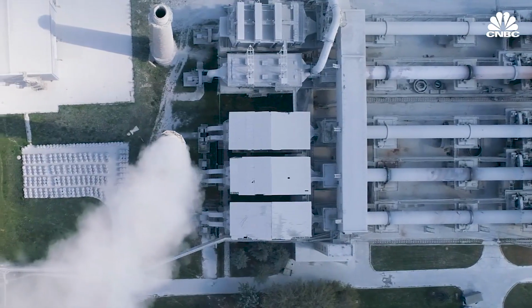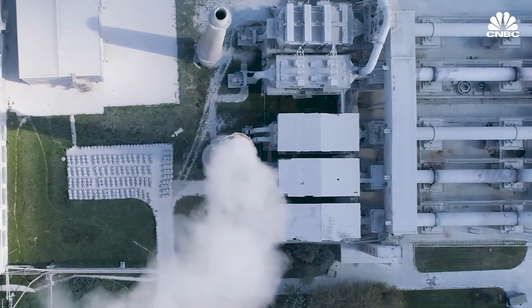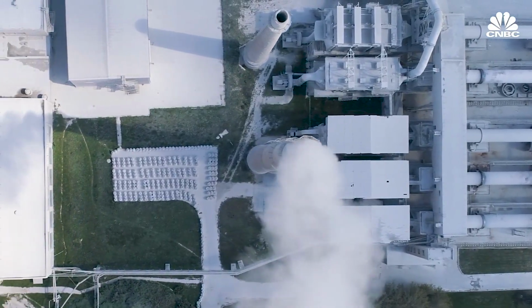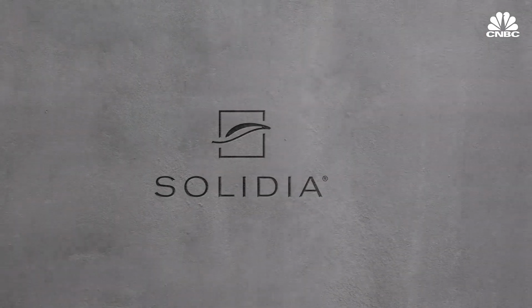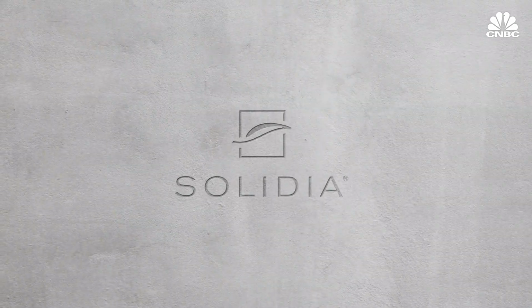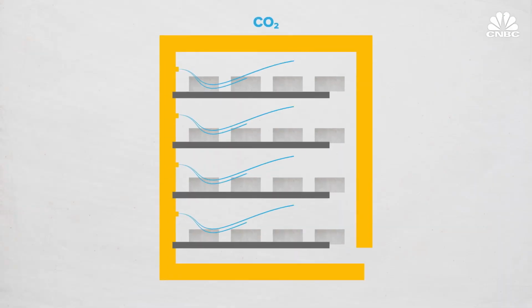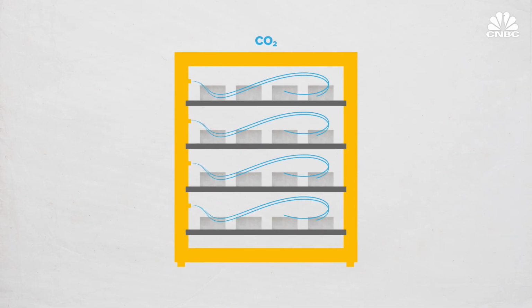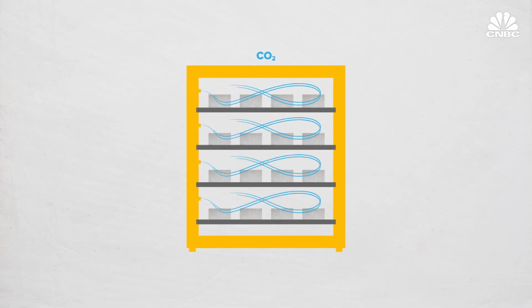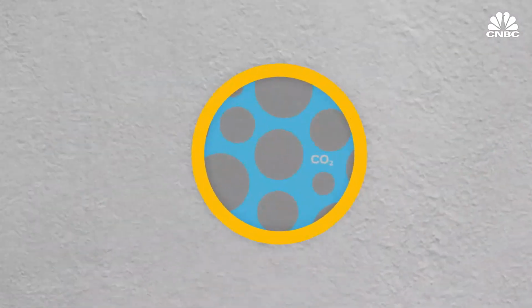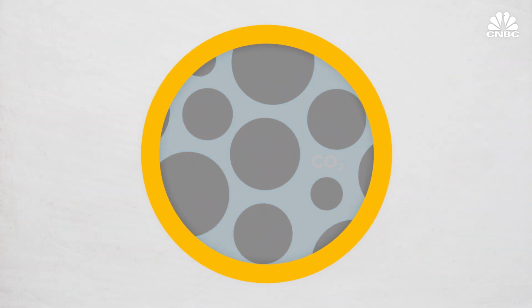Now, what that means to the cement company is instead of emitting 1 ton of CO2 for every ton of cement, they emit about 40% less than that, and they use 30% less energy to make that same amount of cement. They also get more cement with the same amount of raw materials. Solidia cement also cures or hardens into concrete differently than Portland cement, reacting with CO2 that the company injects into a drying chamber instead of with water. As the cement hardens, the CO2 becomes trapped in the final concrete product.